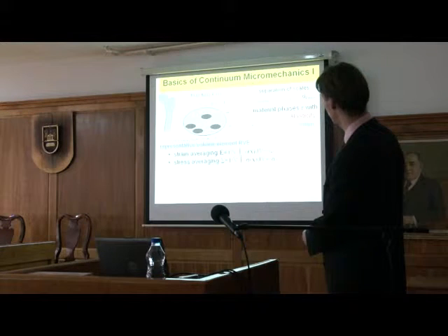Second thing is stress averaging. If the traction forces at the boundary, all related to a macroscopic stress, are in equilibrium with the stresses inside, then the average over the microstresses is the macrostress. And then we need some idea about the fields inside this volume element, and these fields are approximated on the basis of so-called matrix inclusion problems. I don't go into detail.